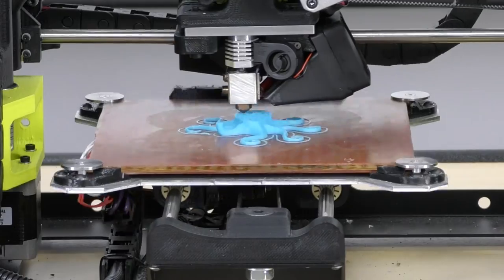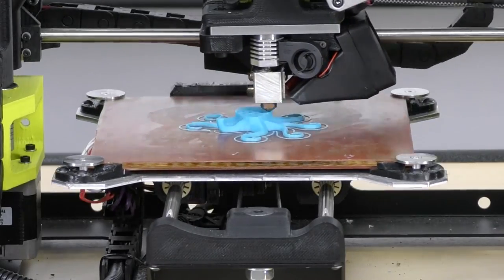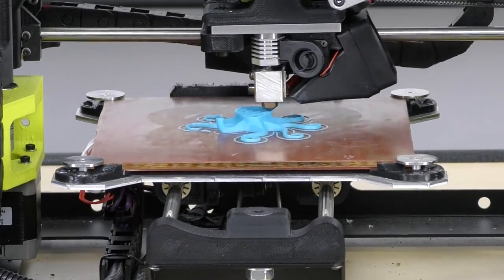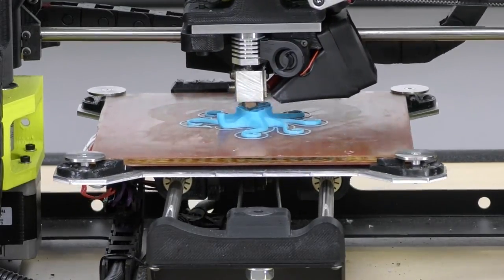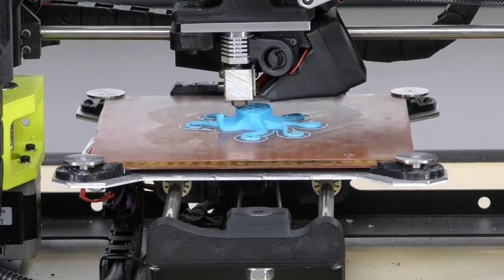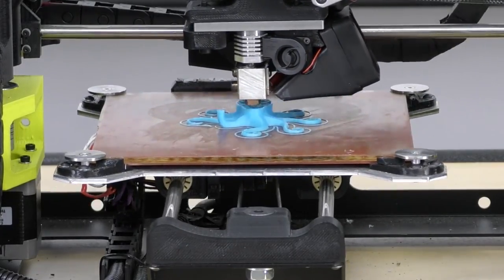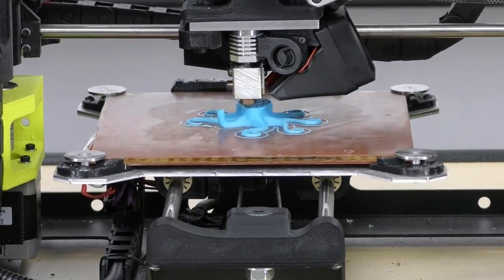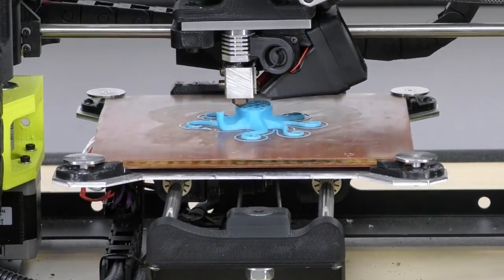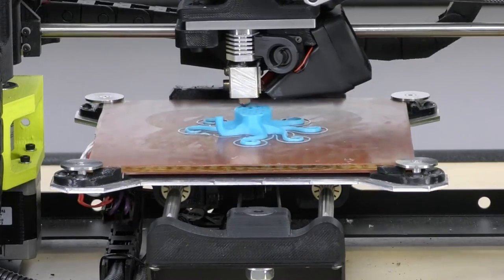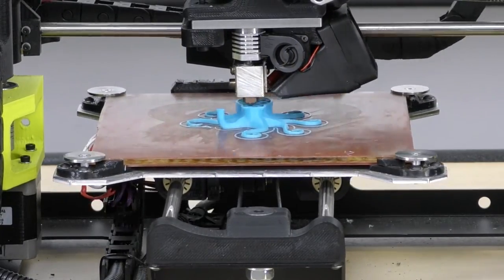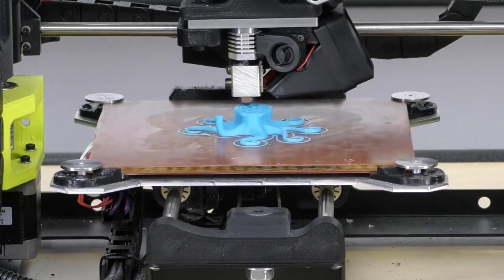Now, there's ways around warping, obviously. It's not something that once the plastic does it, you can't fix that ever. We've got a heated enclosure over in the warehouse, which we use for all our prints with ABS, and it always works really well. We keep the surrounding temperature of the environment at about 40 degrees Celsius, I think we have it set to, and it just holds that temperature. And our prints don't warp at all. And that's all we need.